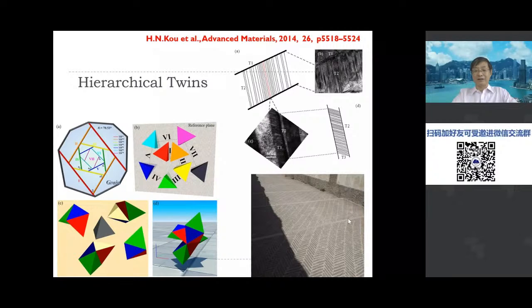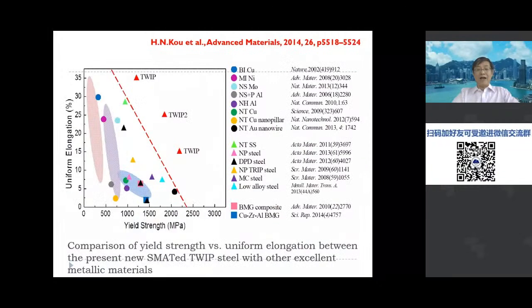To better understand this, you can see this construction. You can imagine all the white areas are twin boundary. As you see, this is a fourth order twin. And then based on this idea, we have achieved the fifth order hierarchical twin. So the hierarchical twin can obtain a high strength, high ductility. The first example is a TWIP steel. We have achieved a high density nanotwin, and the yield strength and uniform elongation are excellent compared to other existing previously published material.